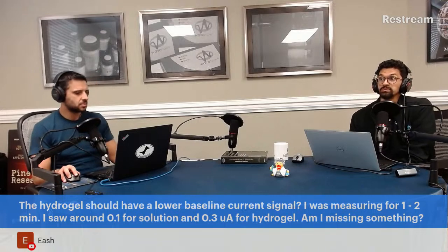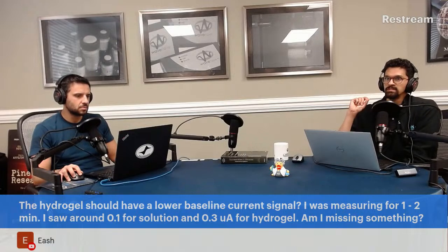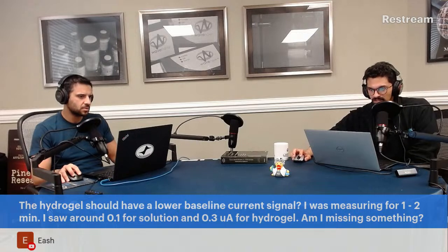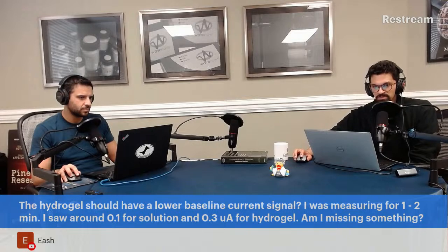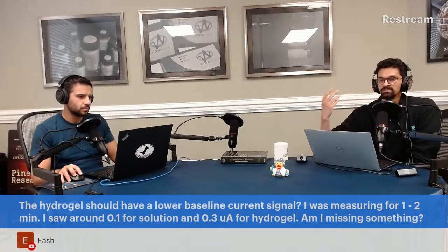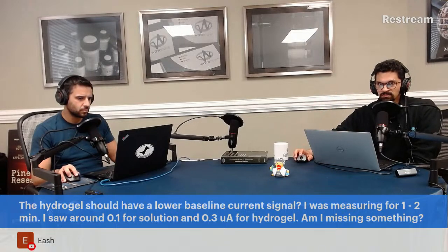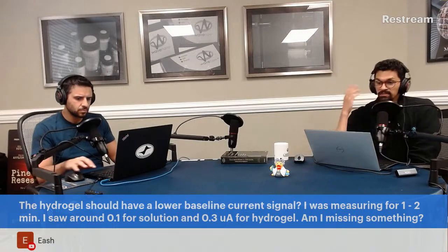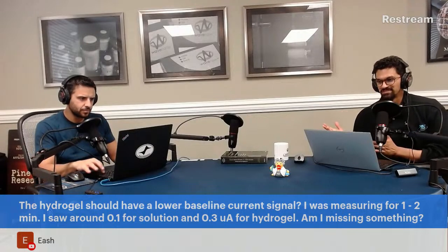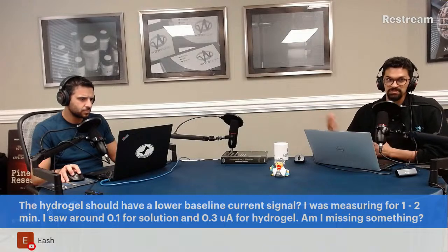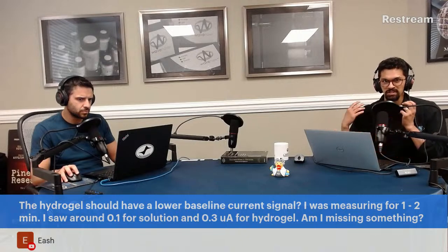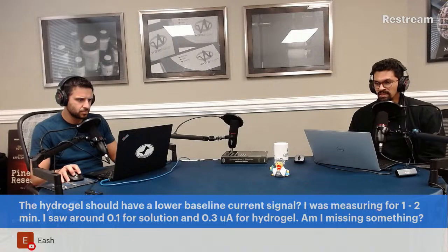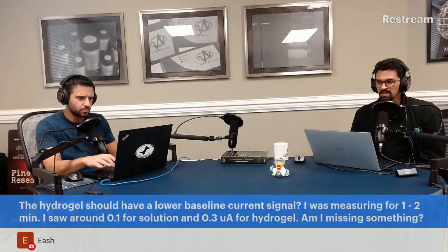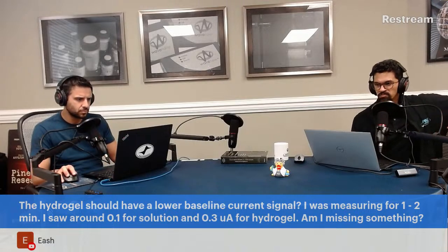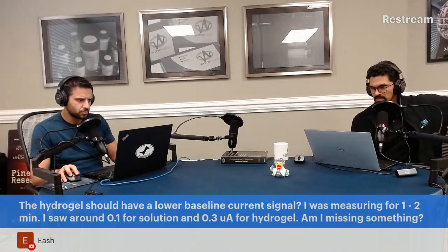I think this is for a reduction reaction specifically. So, hold on. Let me look back. The hydrogel signal was a lower negative current compared to the diffusion coefficient that was faster, so to say. So we had a lower negative current, and mind you, that was just changing the diffusion coefficient, because I thought, if the electrochemical system is exactly the same, except you have a hydrogel versus a regular electrolyte, then that's just my initial guess as to what the values would be. So the hydrogel in this case has more current than for a regular solution.